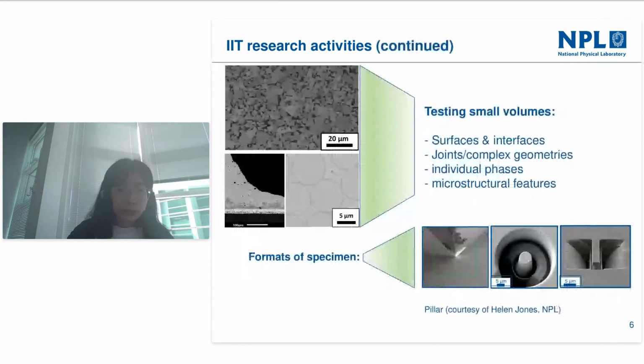Here, this slide gives us, we test small volumes, for instance, the interfaces, joints, and individual phases in complex structures and microstructures such as precipitates. And with the gallium focused ion beam, we can test different specimen formats, for instance, the pillar and the cantilever.